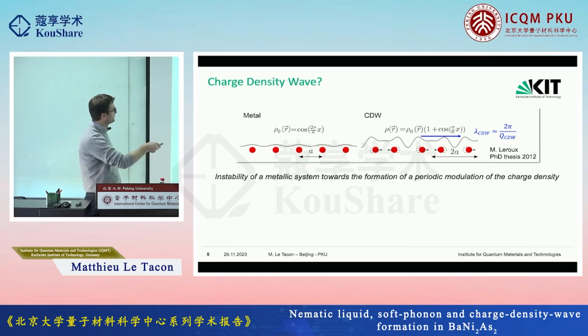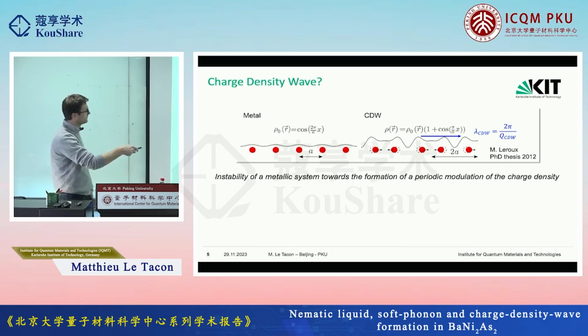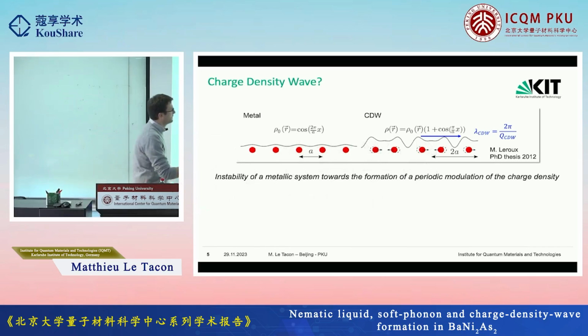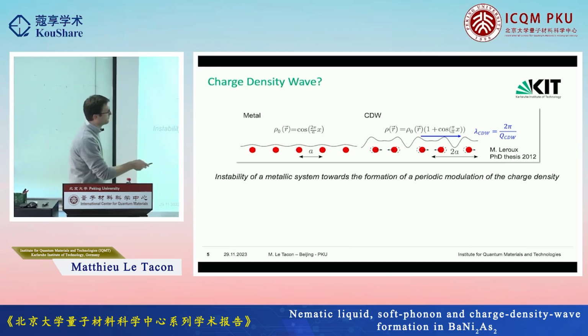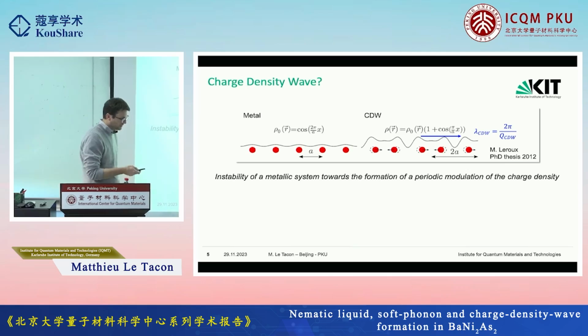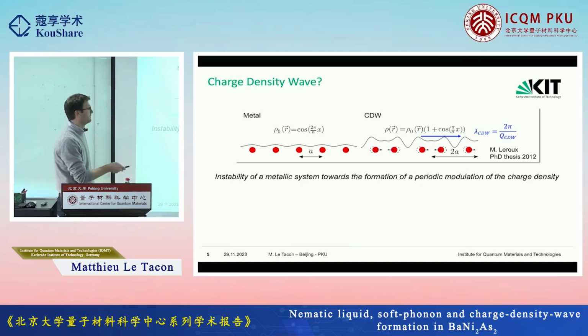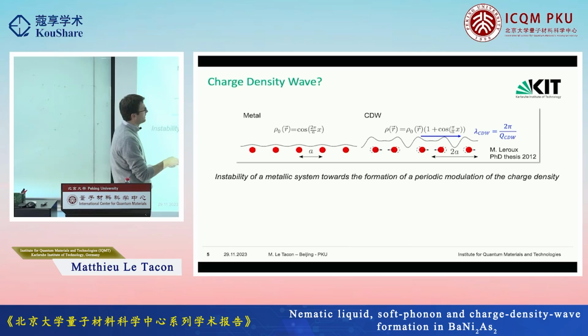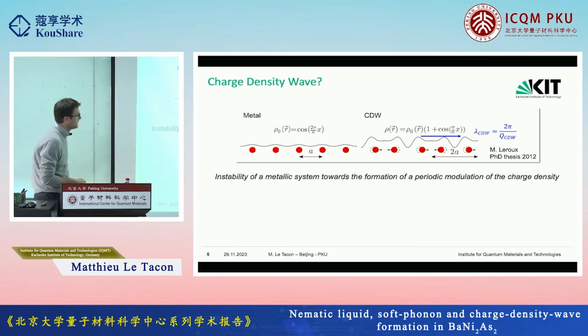atoms with an electron distribution which is modulated following the lattice structure. And you can have an instability, for instance, this Peierls instability, where you have this dimerization, which creates a superstructure, so a doubling of the unit cell. And you can associate that with a wavelength or a momentum, or wave vector, more precisely, that defines the modulation of the order.